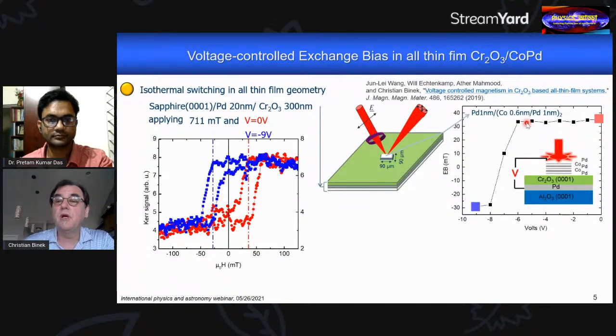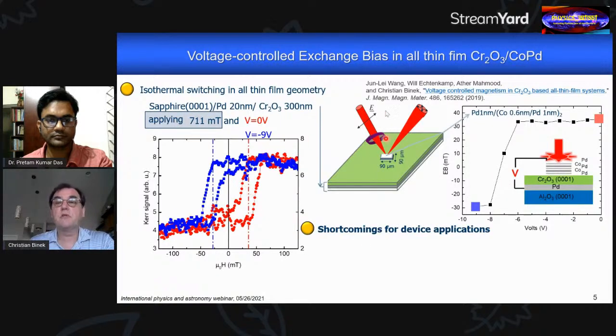But as soon as we reached that critical product value of voltage and applied magnetic field, we were able to switch the system to negative exchange bias. And that was a rather painful way to get to this point. And rather than trying to make devices as I introduced them previously, I will report on shortcomings we identified together with our sponsors from industry, and I tell you about ways to mitigate those shortcomings of this type of devices.